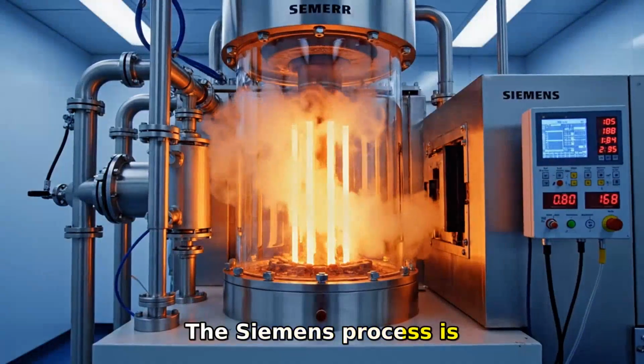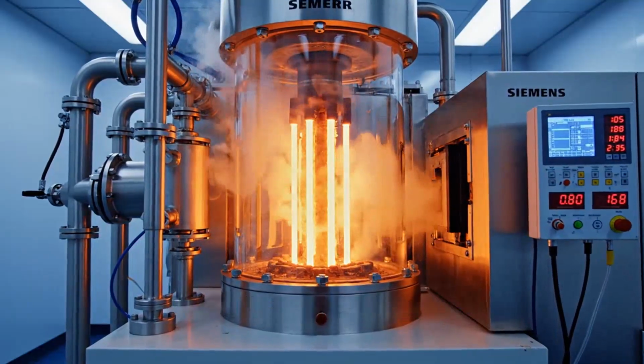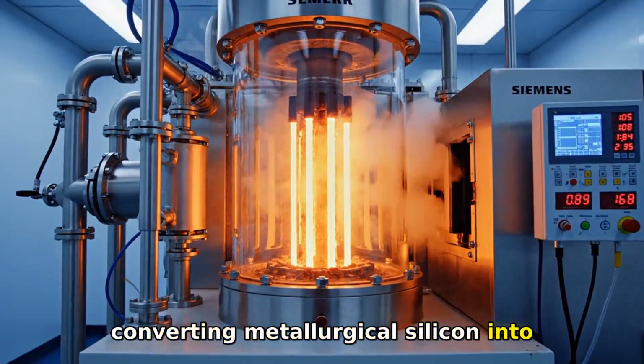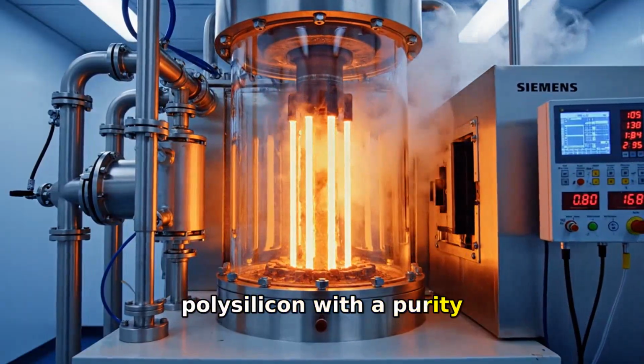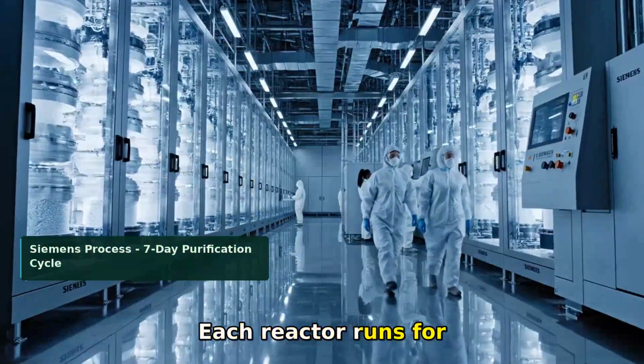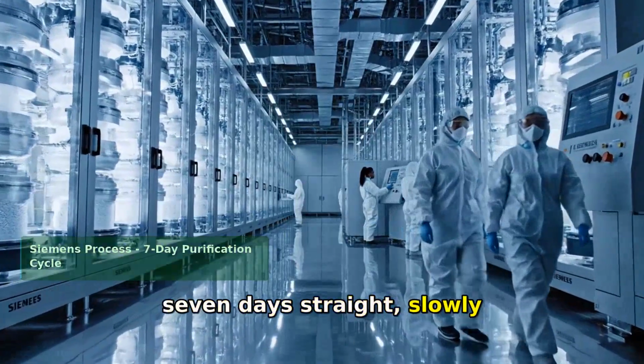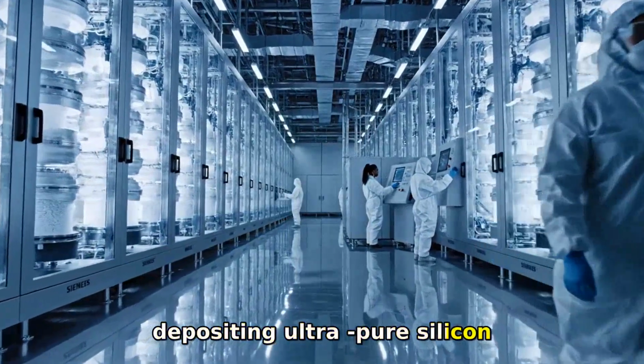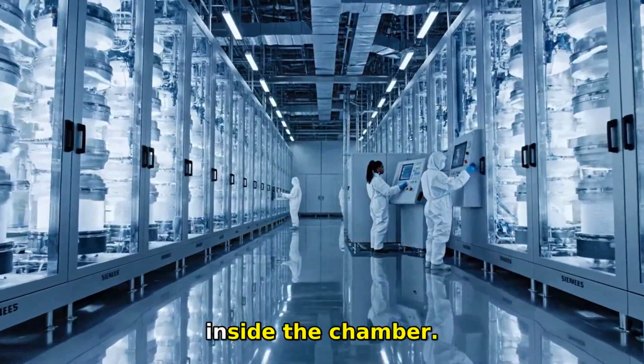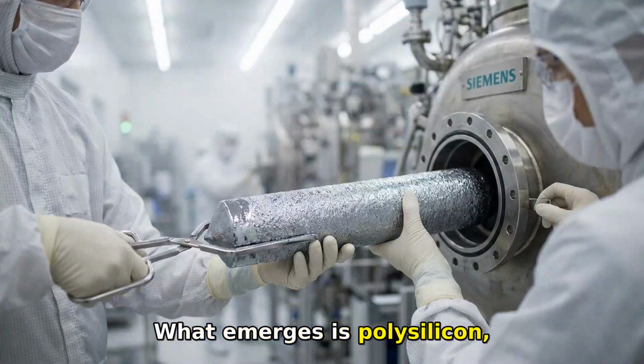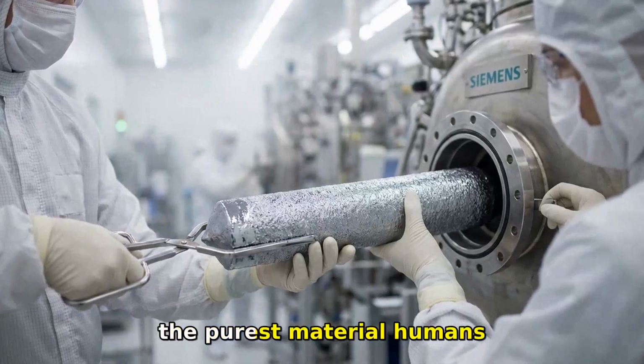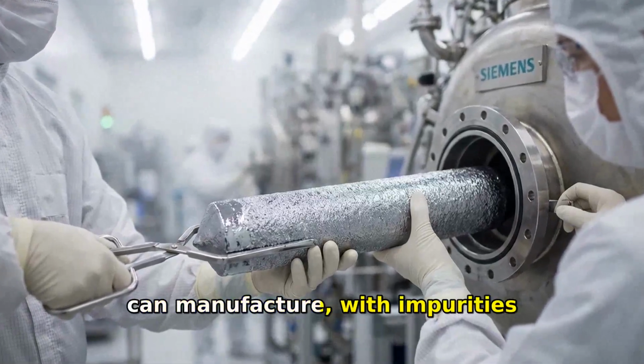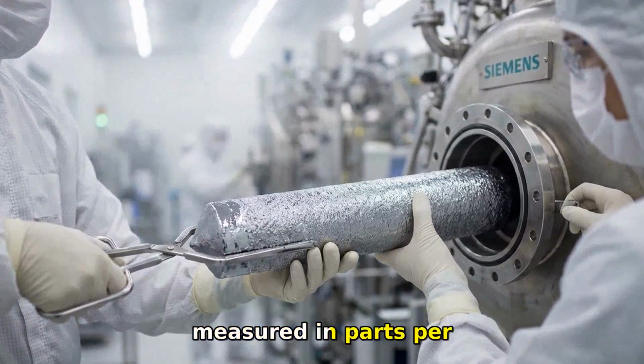The Siemens process is where the magic happens, converting metallurgical silicon into polysilicon with a purity of 9 nines. Each reactor runs for 7 days straight, slowly depositing ultra-pure silicon onto thin seed rods inside the chamber. What emerges is polysilicon, the purest material humans can manufacture, with impurities measured in parts per billion.